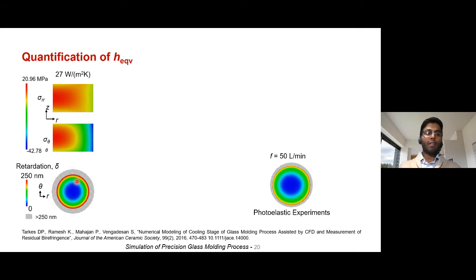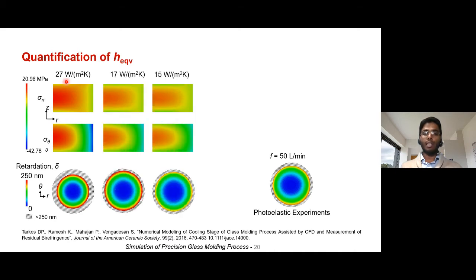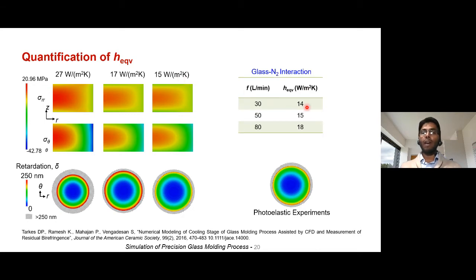I simulated the birefringence data and compared it with the photoelastic experiments, and very clearly you can see that it doesn't match very well. So what I did is, using a reverse approach, since we have the experimental data, I tweaked the value of H equivalent until it matched with the experiments. What we found is that for the flow rate of 50 liters per minute, the value was about 15 watt per meter square Kelvin. And similarly, for the different flow rates, the values were estimated as shown in this table.